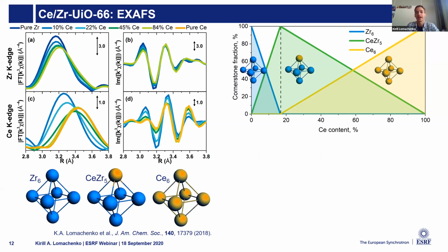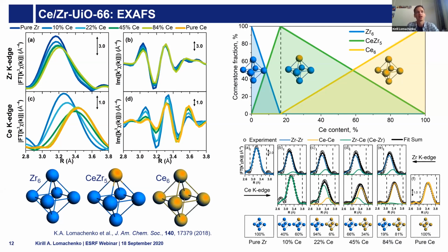So 10 different spectra, and we find that the quantitative agreement of this model with our hypothesis is very good under realistic physical constraints.